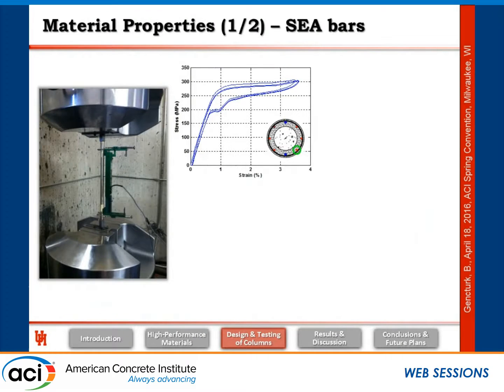Before I move on and show you the results from the column testing, I would like to show you some of the material tests we have done. Since I mentioned that these bars are not so robust like the nickel titanium ones, we wanted to make sure that they will not rupture. Some of them had some premature rupture, so you just take the material, you load it very slightly, like 1%, 2% strain, and it ruptures. So to make sure that these are not those bad ones, we tested each and every bar that we put inside the columns.